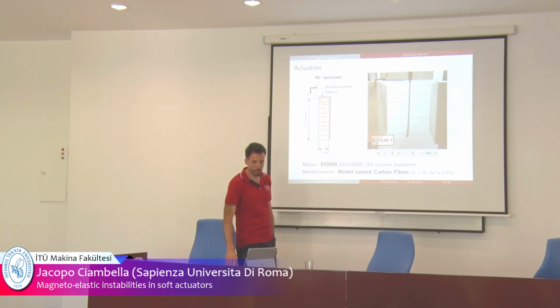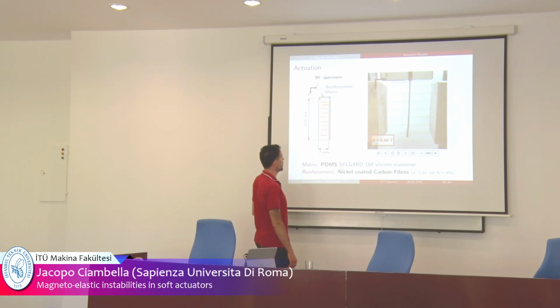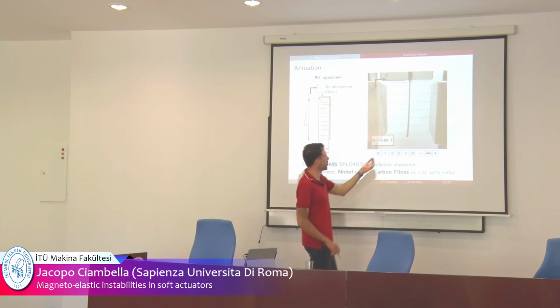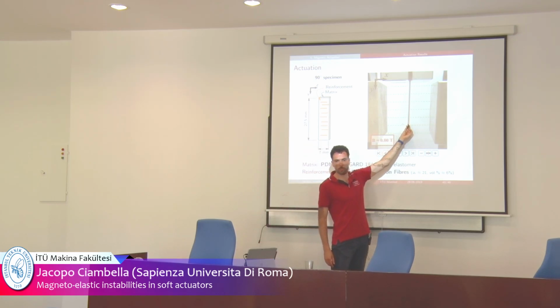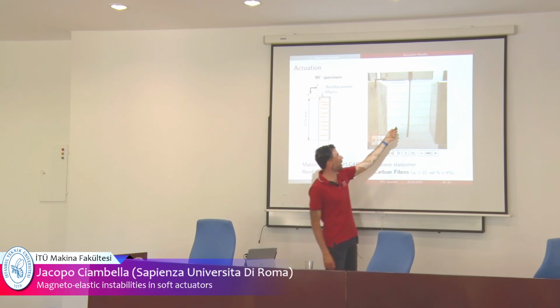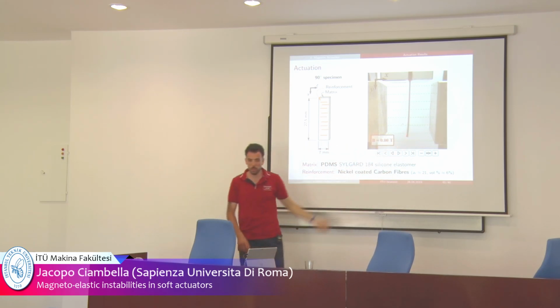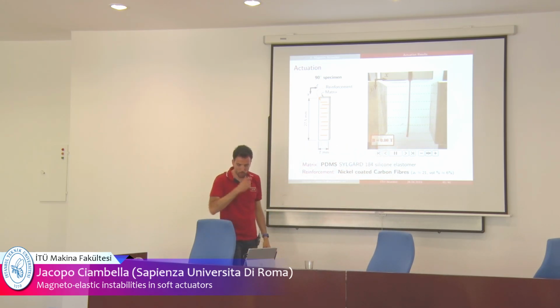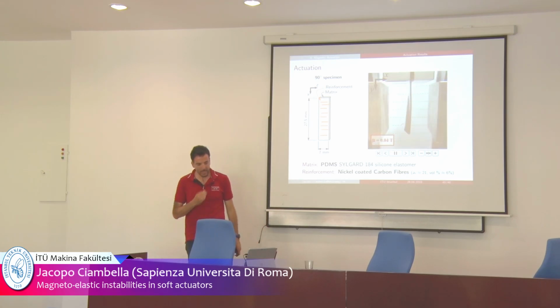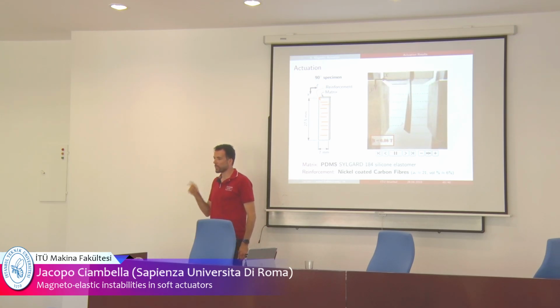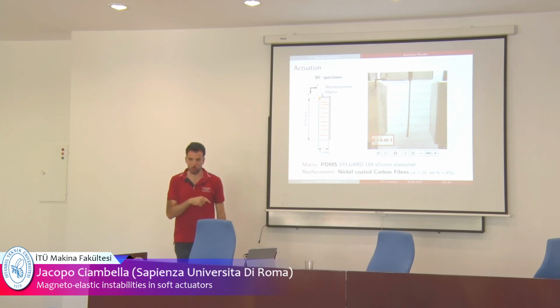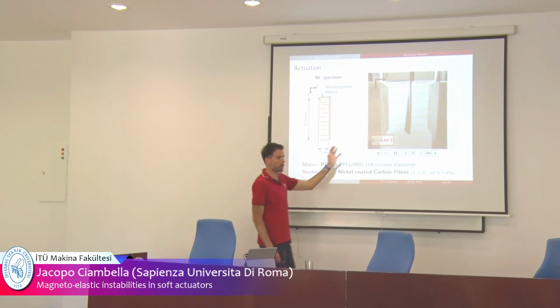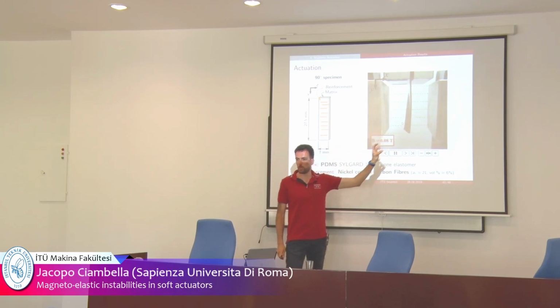And the same thing happened for this other specimen here, where you have fibers at 90 degrees. Again, 90 degrees means they are orthogonal to the field lines in this direction here. Okay? This is, again, clamped. This is a free end. And this is what we have seen. Nothing happened. But then at a certain level of the magnetic field, which was different from the previous one, the specimen twisted immediately. Okay?